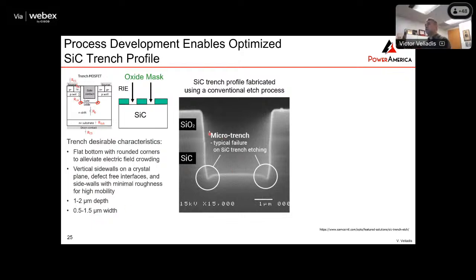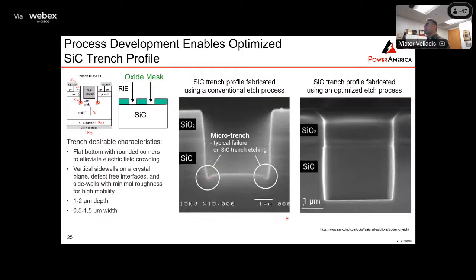And here's an example of a trench. You see the oxide here, that's the hard mask, the silicon carbide below. But this is not an optimized etch. You get these microtrench features right here, highly undesirable, and it's not very vertical. But if you spend the time and work with the equipment manufacturer, you can get something that looks like this. Now you can see here, the sidewall is vertical. The roughness on this sidewall is very low, and you're getting this nice rounded corner for the trench, which will help you minimize the electric field buildup. Okay, so that's how you do the trench in silicon carbide.